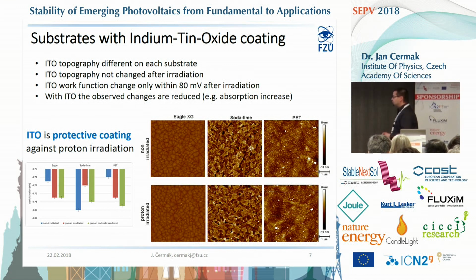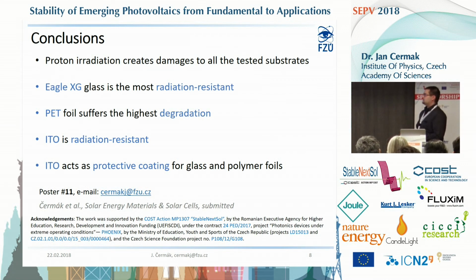What is even more important is that the degradation observed on the bare materials, like the increase in absorption, the coloring, and so on, is quite reduced in the presence of the ITO coating. Therefore, we may claim that ITO is not only a conductive coating, but it also works as protection. That is actually the final thing I would like to say. These are the conclusions. Protons are quite dangerous to the tested materials. Eagle XG glass seems to be highly resistive. PET foil in its bare form is very damaged by protons, but the ITO coating might help a lot.